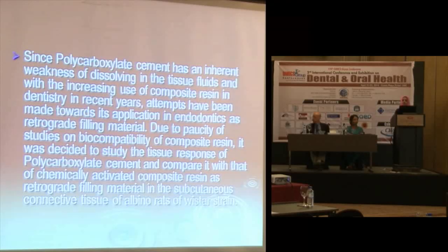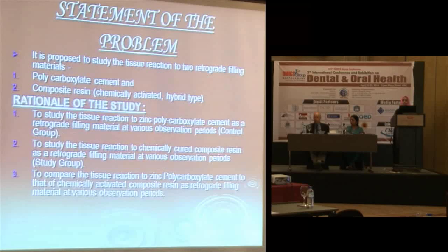Due to paucity of studies on biocompatibility of composite, it was decided to study the tissue response of polycarboxylate cement and compare it with that of chemically activated composite resin as retrograde filling material in the subcutaneous connective tissue of albino rats of Wistar strain. Statement of the problem: it is proposed to study the tissue reaction to two retrograde filling materials, polycarboxylate and chemically activated composite resin. First, to study the tissue reaction to zinc polycarboxylate cement as a retrograde filling material at various observation periods. This was the control group. Then to study the tissue reaction to chemically cured composite resin at various observation periods. This was the study group.